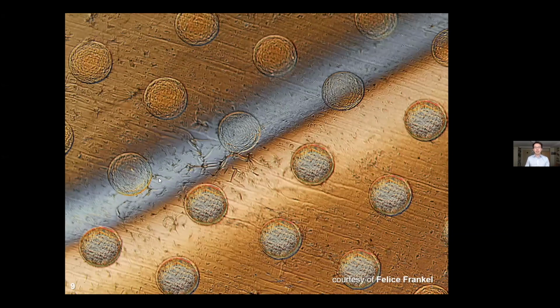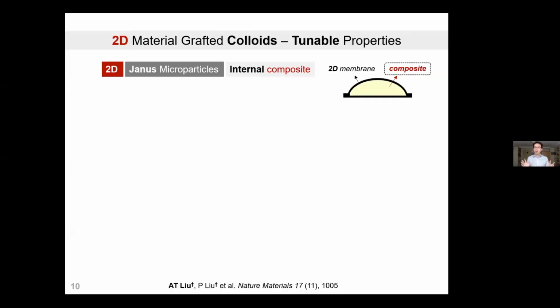This is actually a beautiful picture that was taken by our colleague Felice Frankel inside her studio, where you can see this stripe, which is the lift-off solvent, this mechanical shockwave that we create to generate, or nucleate, the initial seed cracks. You can see the crack starts to form on top of this shockwave, and then, in the process you already saw on the previous slide, it starts to propagate and cut across the circularly shaped pattern to form these colloidal electronic devices. So we're not doing anything crazy here. All we're making is basically this 2D membrane encapsulated composite.